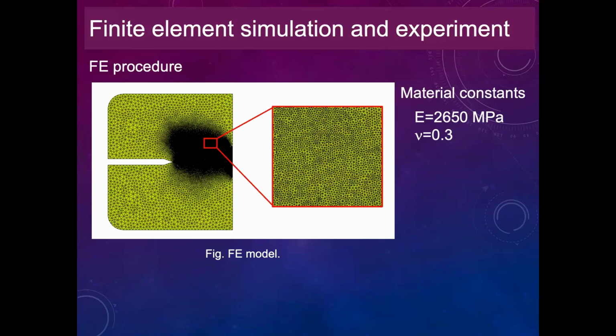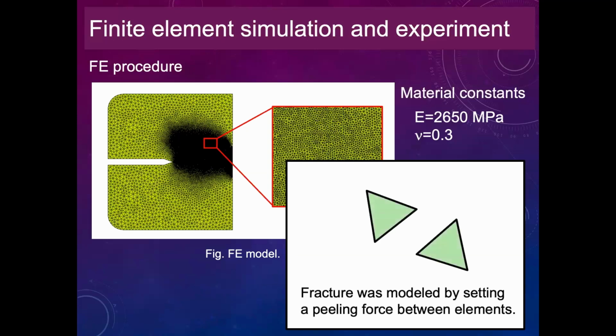Those values were identified during the tensile test, and we compared the FEM results and the tensile test results for the base metal. Also, in order to express crack initiation and propagation in the CT specimen, the fracture was modeled by setting the peeling force between the elements as shown here. The peeling force sigma normal to the edge of the element was set to 100 megapascal, and the one parallel to the edge of the element was set to 150 megapascal. Those parameters were identified by comparing the FEM analysis and the experimental observation result during the tensile test.